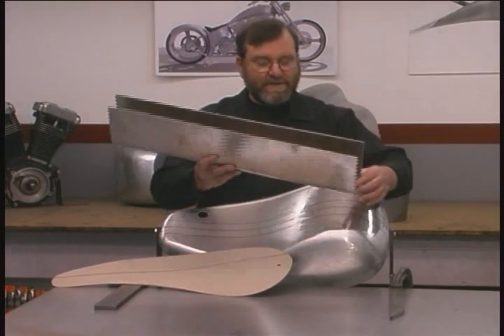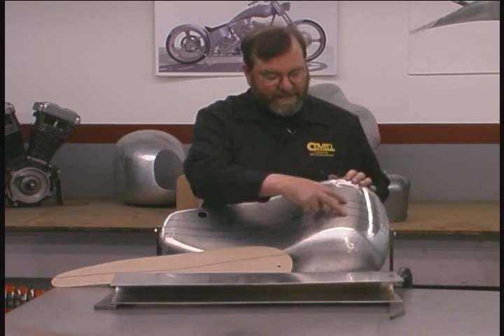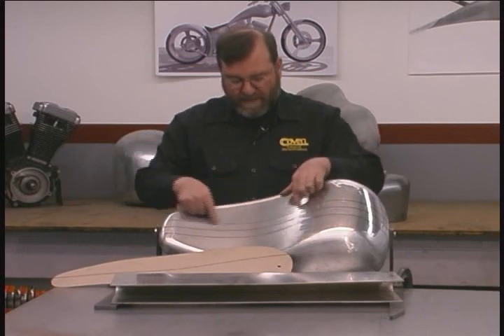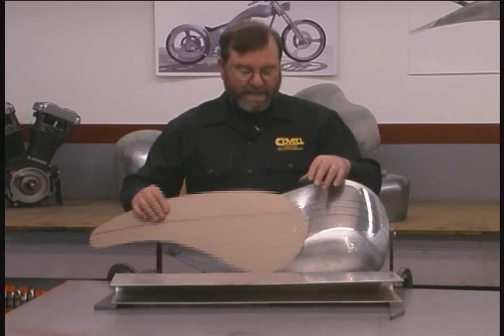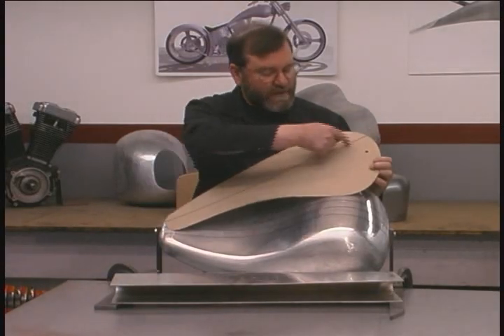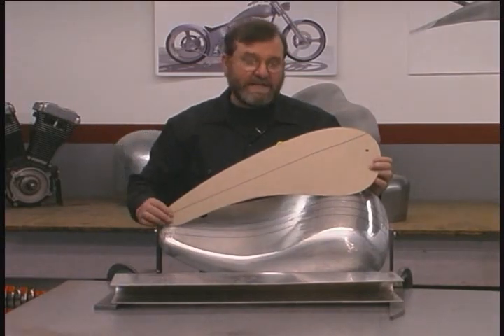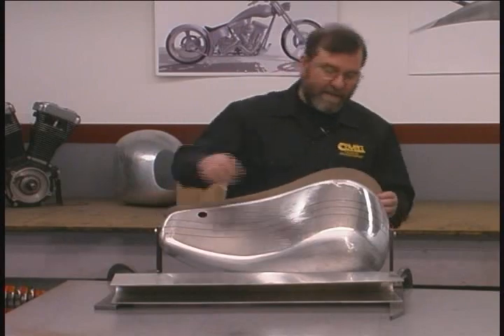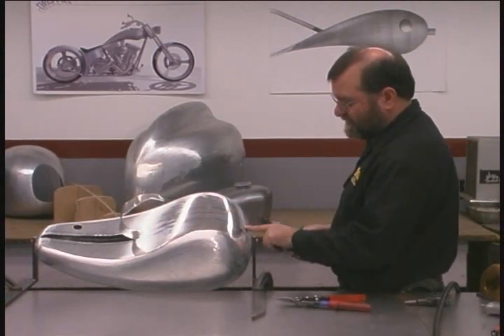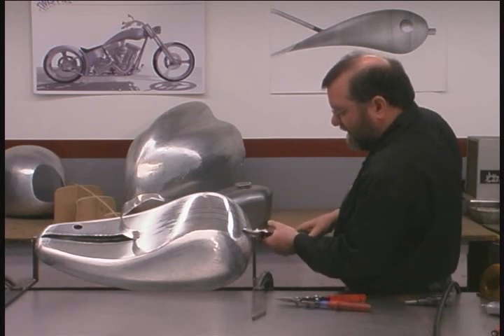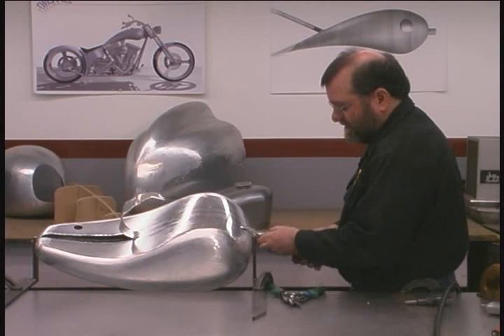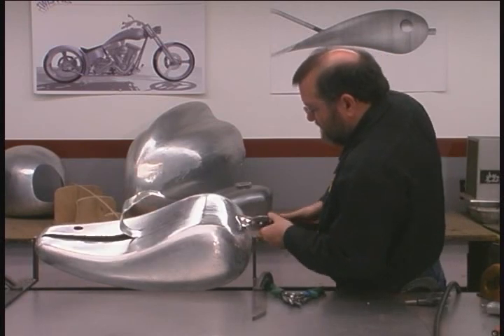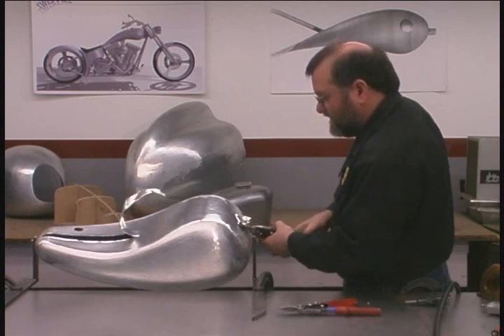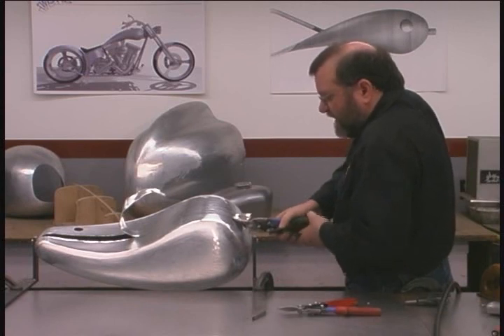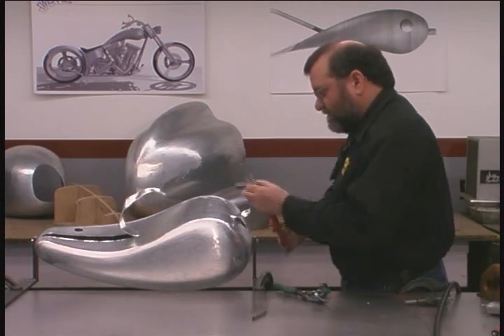So this tunnel is 2 1/4 inches wide. I've made 2 marks on my tank, 2 1/4 inches wide. We can trim the tank on these marks to fit the tunnel into place. Remember when we started the tank project, we made a pattern that had a reference line in it, showing where the top surface of the top tube of the chassis rests in the tank. This is our reference for knowing how deep the tunnel is cut into the tank, both front and rear. A convenient way to remove the material for the tunnel is to drill a pilot hole first, and then cut a strip of metal out using your left and right aircraft shears. This is a roughing cut, so I'm leaving about a 1/4 inch of material right on the line for our finished cut. But this is a good way to get rid of the waste.